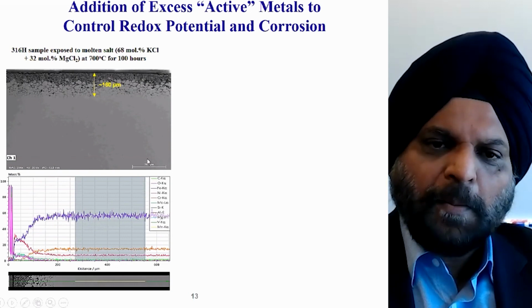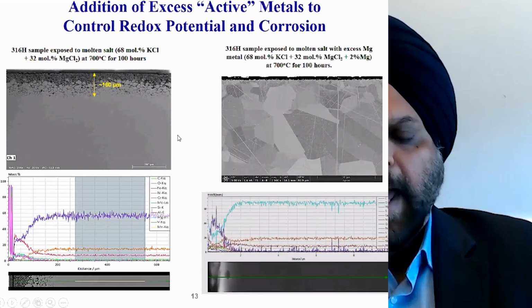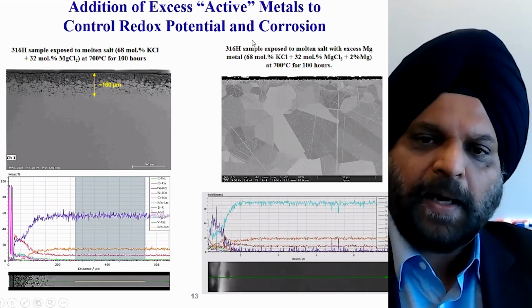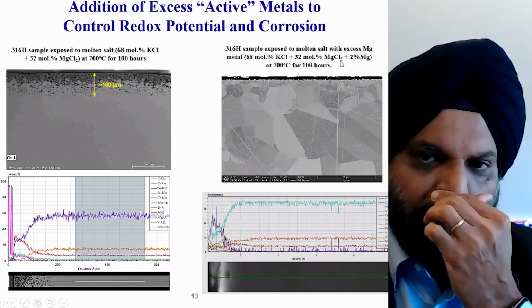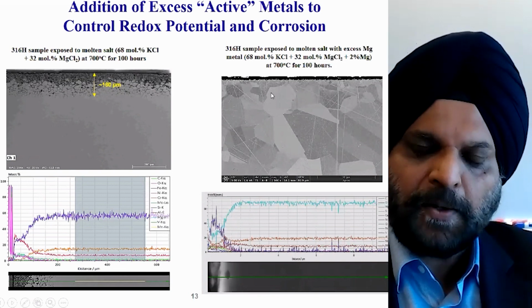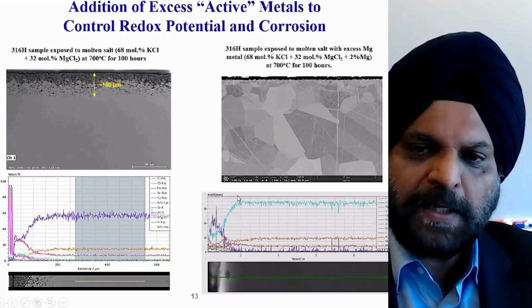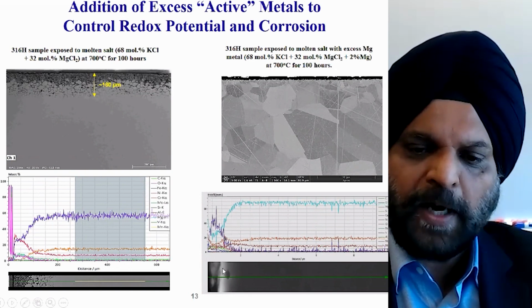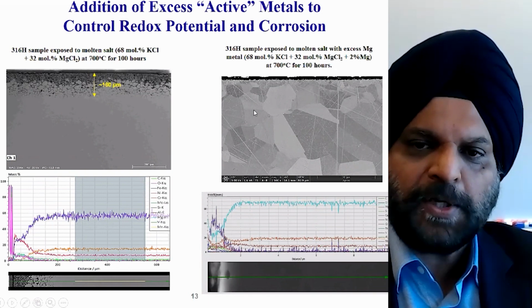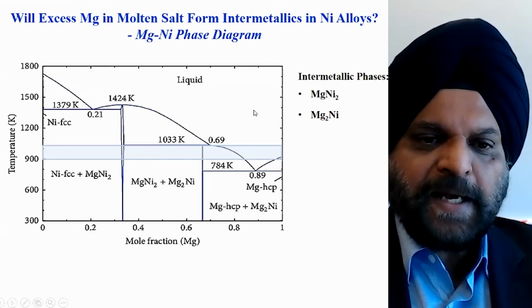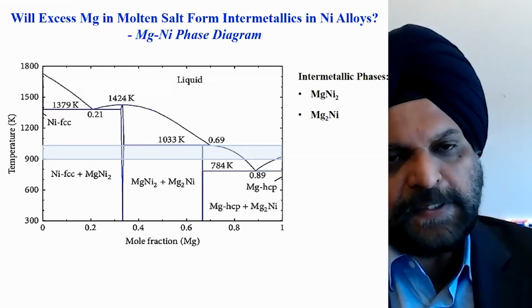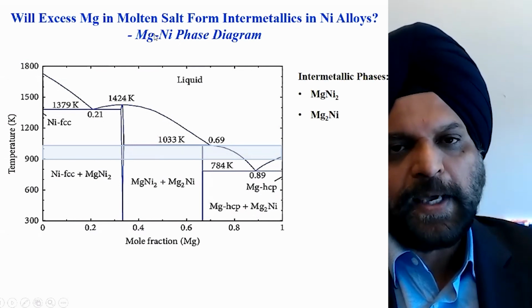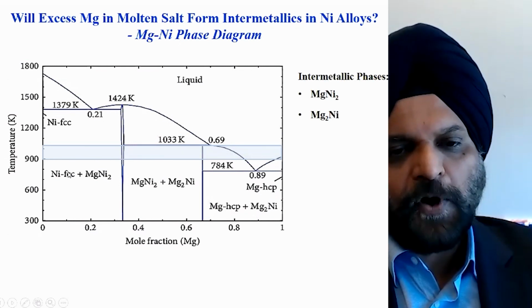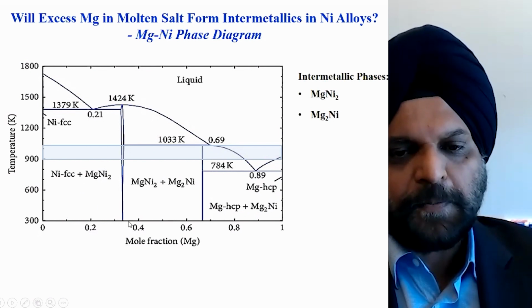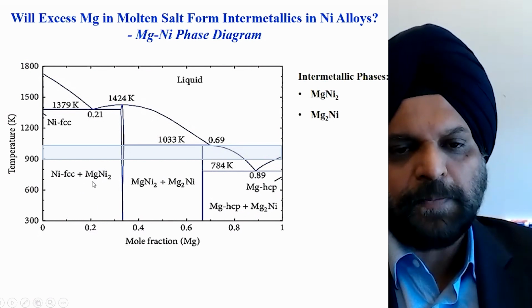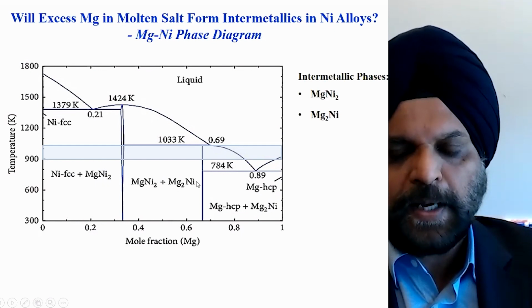But as soon as you start to add magnesium, and if you add a significant amount, you actually stop that corrosion almost completely. There's a very narrow zone of about 2 microns where you still have some chromium depletion. The problem is that magnesium, if it's in excess, can also react with the alloying element nickel, and it can form magnesium-nickel intermetallics depending upon how much magnesium is there. It can be MgNi2 or Mg2Ni.